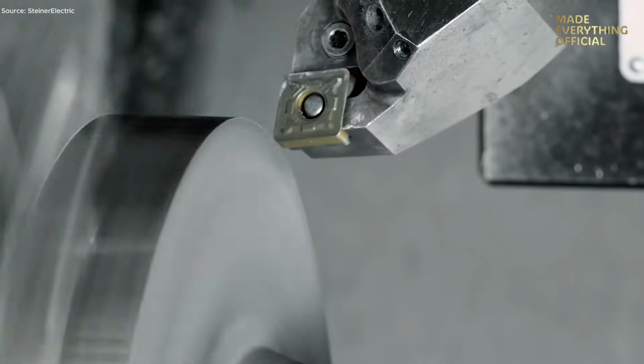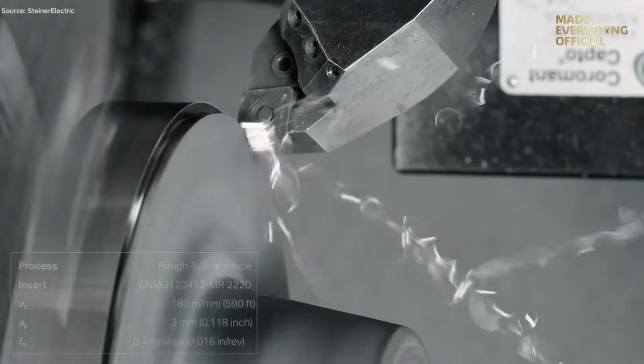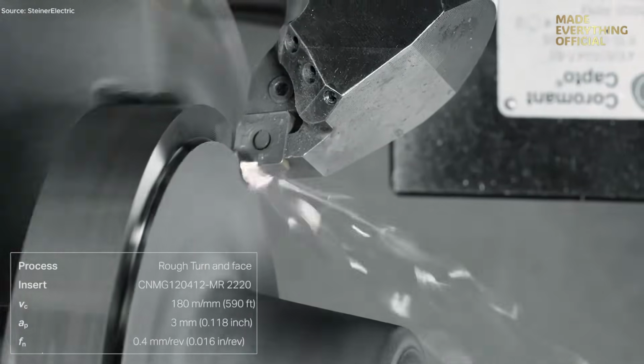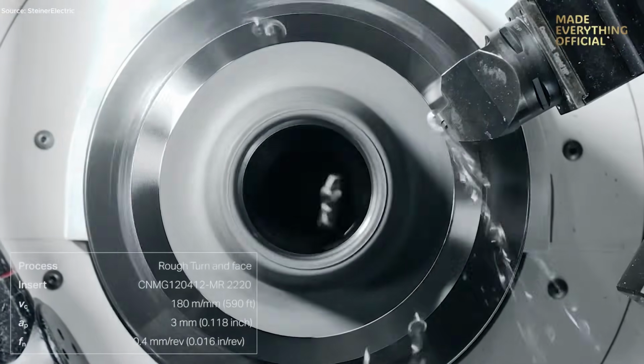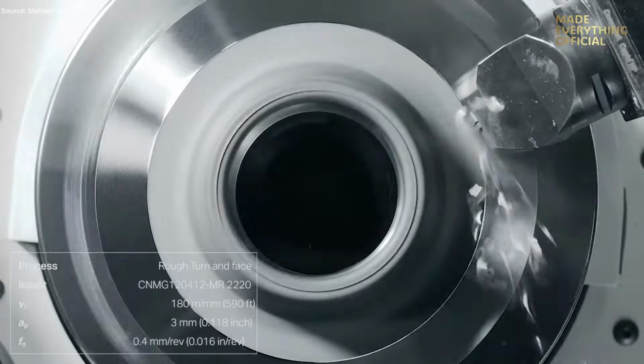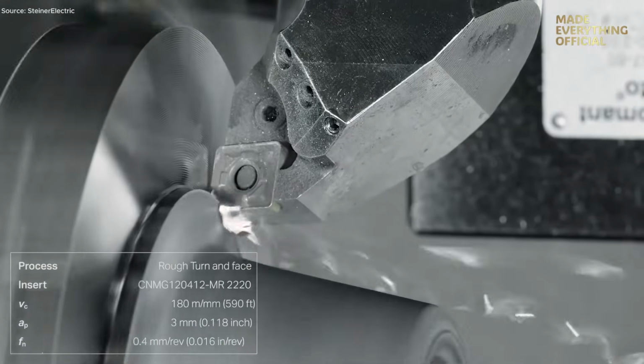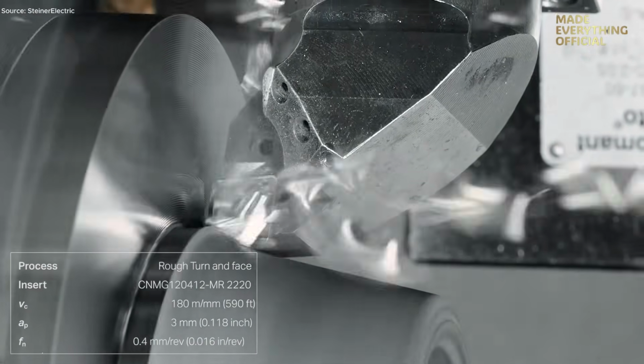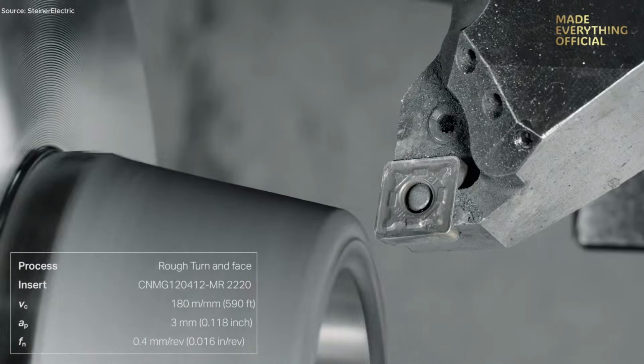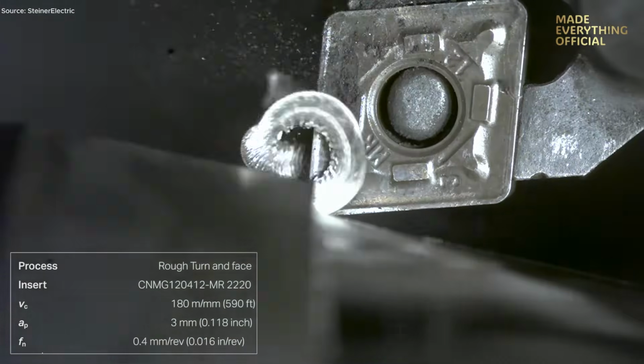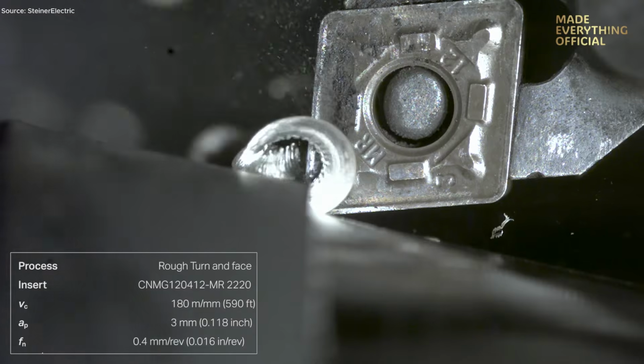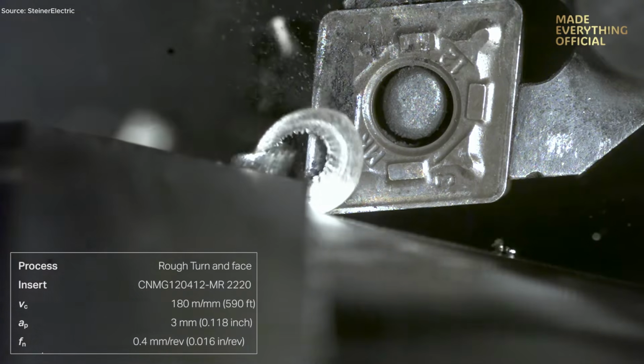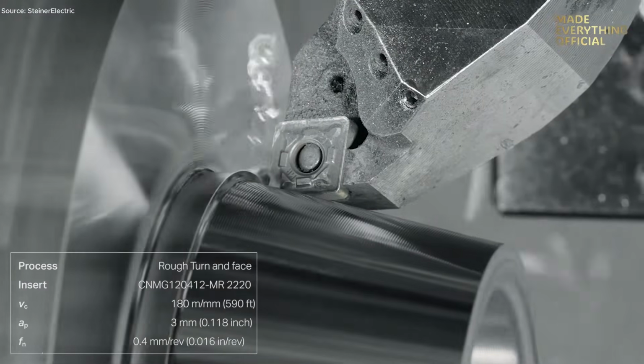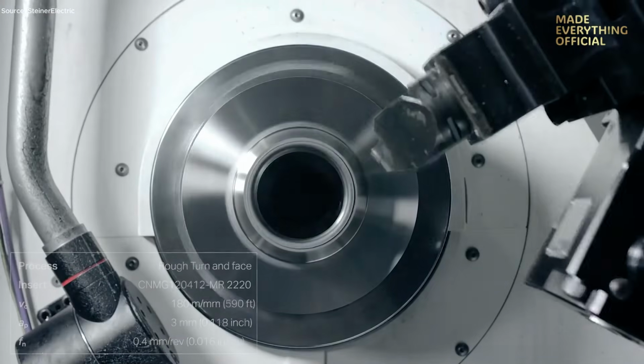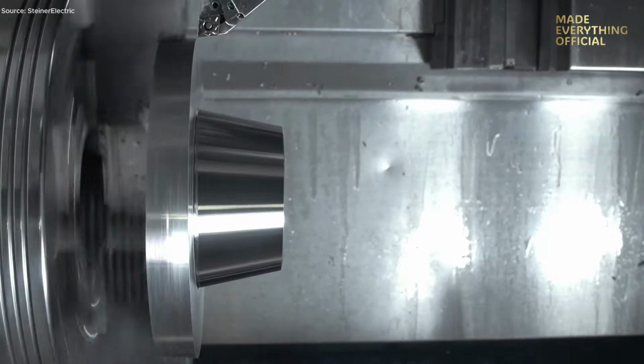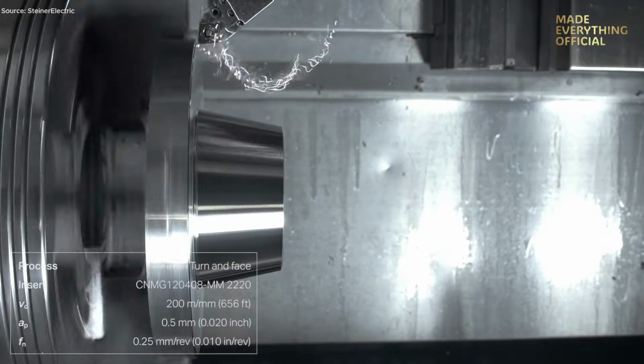Metal shaping begins here, where precision meets raw power. This CNC lathe operates with a CNMG 120412MR 2220 insert, performing a rough turning and facing sequence. The cutting speed reaches 180 meters per minute, removing material at a depth of 3 millimeters with a steady feed of 0.4 millimeters per revolution. Each pass generates a shower of glowing chips, pure energy sculpting cold steel into form.